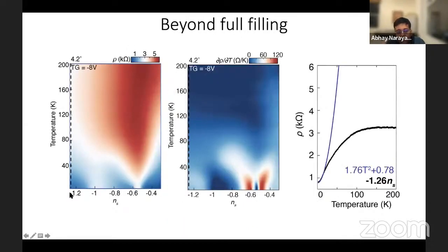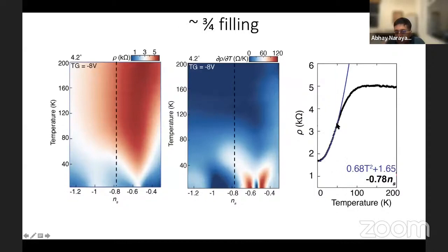If I sit very, very far from this insulating phase, and I measure the temperature dependence of resistivity, and I look at low temperature, then you can perhaps see this little curving of the resistivity at low temperature, and it's reasonably well fit by a T-squared form with some coefficient. As I start to approach this insulating phase, you can see much more clearly a beautiful T-squared form at low temperature. So this is somewhere close to, but not very close to the metal to insulator transition.